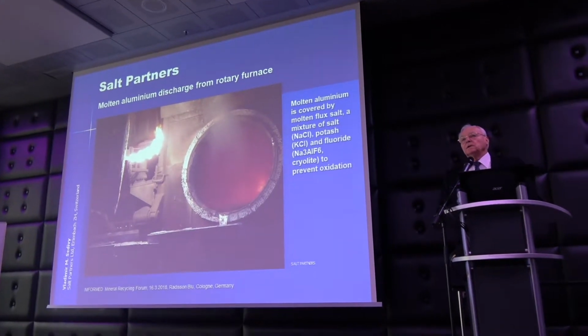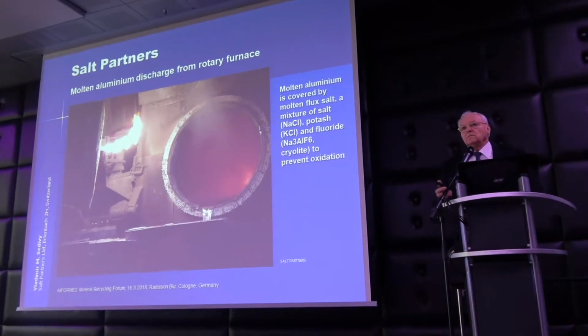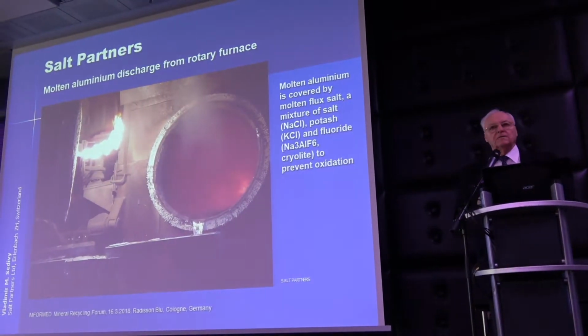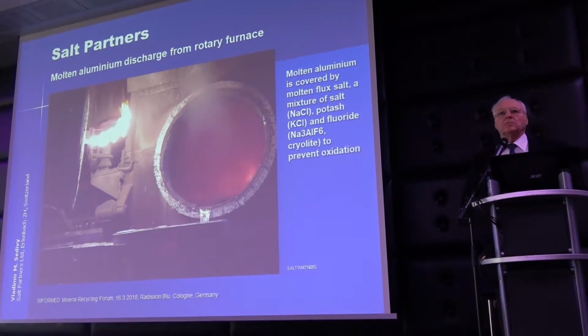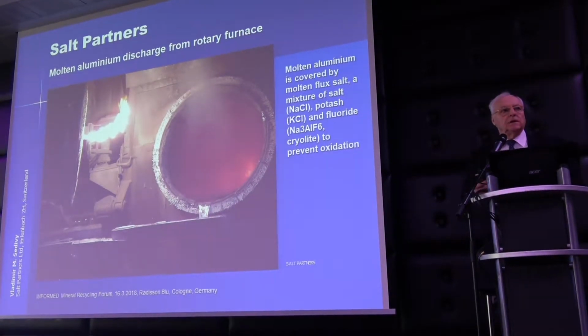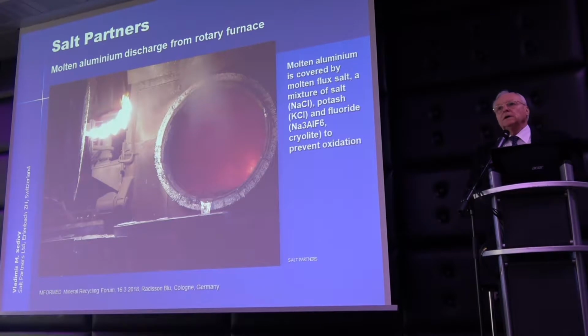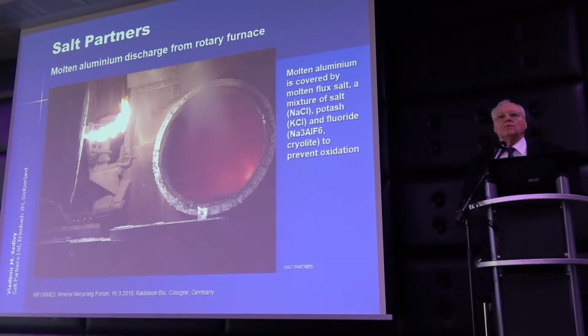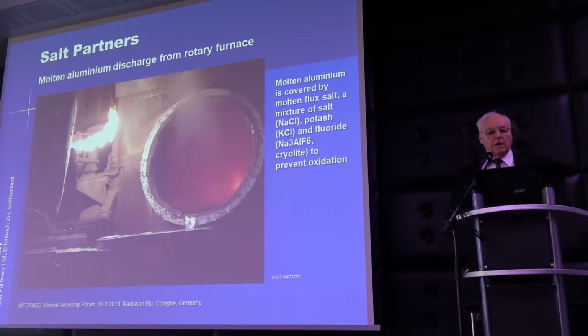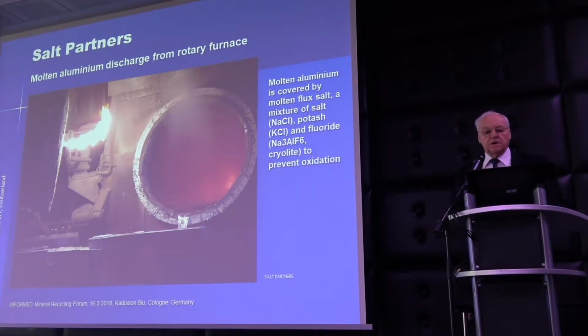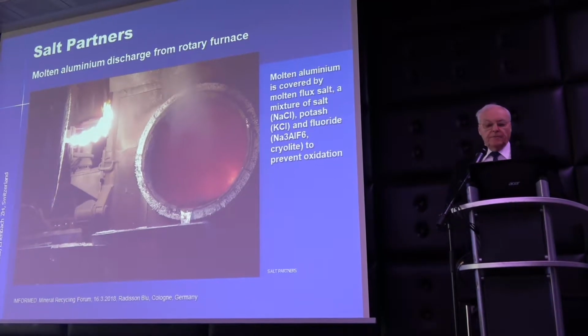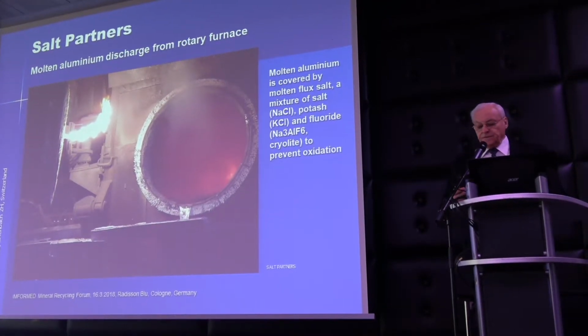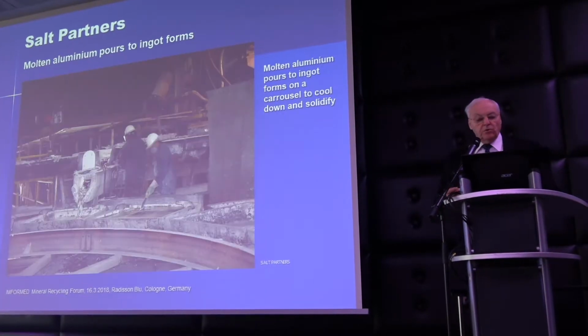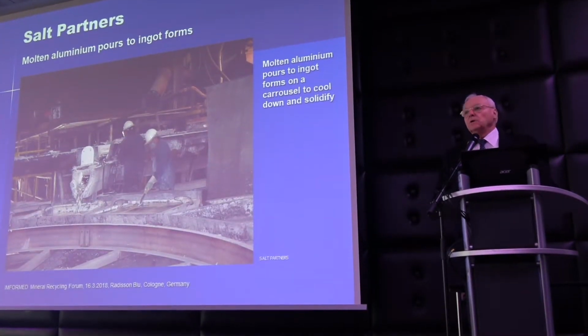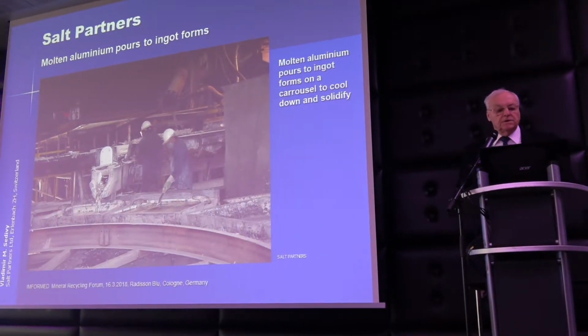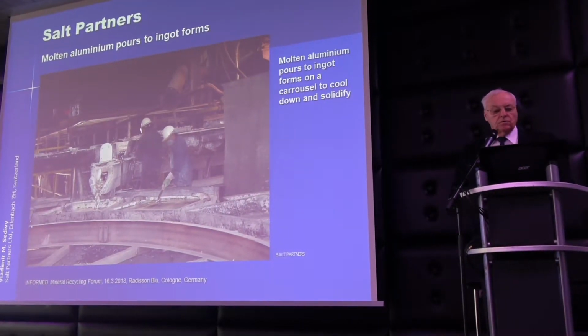In the rotary oven, the waste aluminium is fed in and melted, heated up, and to avoid the oxidation of the aluminium, it is covered with a mixture of sodium chloride and potassium chloride, plus about 3% of cryolite, the fluoride. And after the aluminium is poured out, this shows how the aluminium is being poured into the forms to form the ingots.